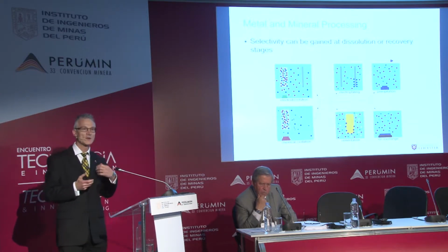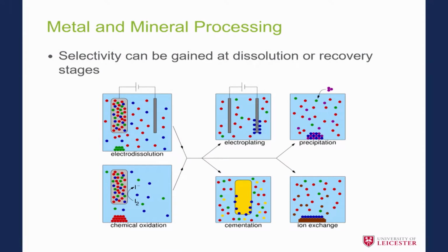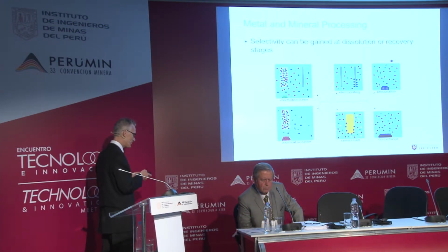Okay, so this shows the sort of selectivity we have as a result of the various flexibility in what we can do. So what we're trying to do here is we're trying to recover the metal value. And we have two modes of dissolving our mineral. We can make our mineral an electrode and add or subtract electrons and cause it to go into solution. Alternatively, we can use a chemical oxidizing agent, and we use dominantly iodine, which is very environmentally benign and safe. Okay, so we can oxidize it into solution.